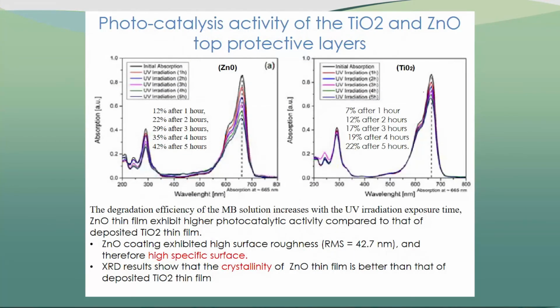So we also studied the photocatalytic activity of these two thin layers, and we saw that the methylene blue degradation for different hours was much more interesting for the case of ZnO, and we see that after 5-hour exposure, 42% of the methylene blue was already degraded, which is good. So ZnO was much more interesting.